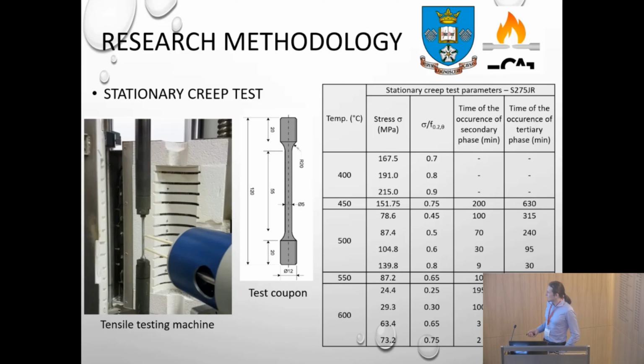For the stress levels that we've chosen, you can see the utilization ratio with respect to the stress at 0.2% strain at the temperature level that's being tested. We've tested at 400 degrees with stress levels which are really high, and gradually decreased the utilization ratios of the coupons when we arrive at 600 degrees. You can see on the right-hand side of the table the occurrence of the secondary and tertiary creep phase.